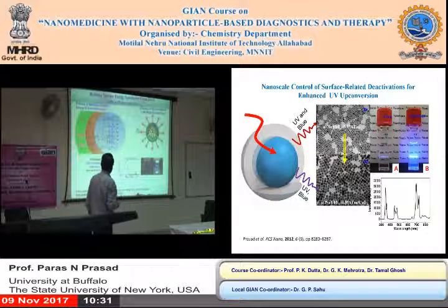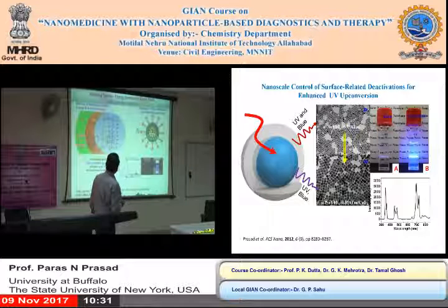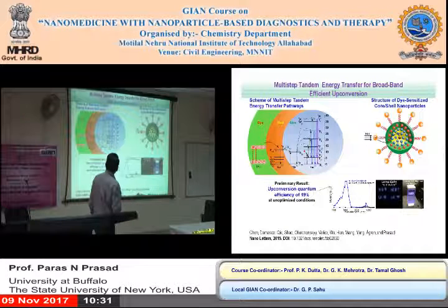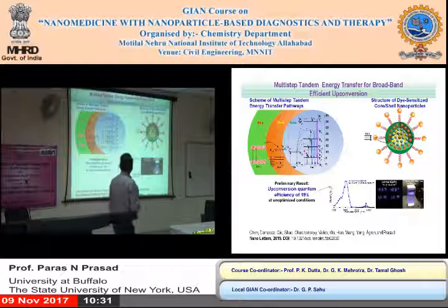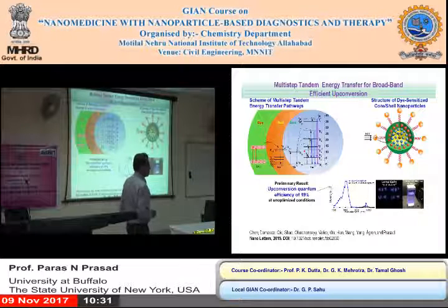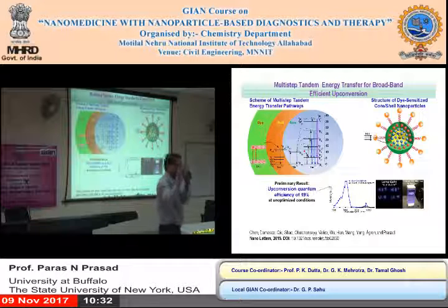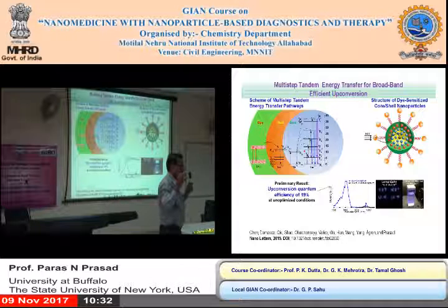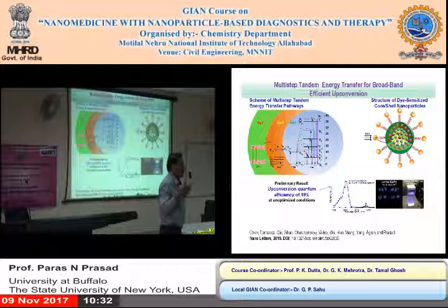Another thing we showed: if you take rare earth ions, this is the emitter thulium. Ytterbium is what we call the sensitizer. Light is generally absorbed by ytterbium at 980, and that transfers to thulium to climb up and emit from different levels. But this absorption by ytterbium or thulium is again F to F, and that transition is not very strong. Organic dyes are very strong absorbers.